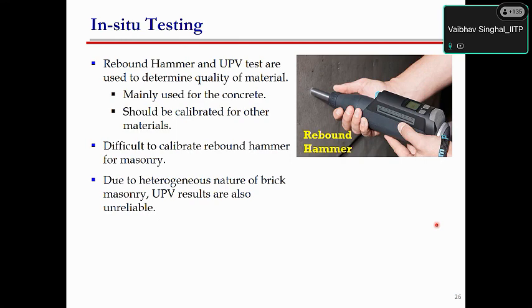You cannot use them, because the rebound hammers which are available are mostly calibrated only for concrete. So you have to either calibrate it for a particular type of brick, or you need to test a lot of bricks and then find out some kind of calibration curve, so that if the rebound values are these, this can be interpreted as this much brick strength. So a lot of data has to be collected, and the rebound hammer has to be calibrated for masonry structures. But the challenging thing is that you can only know the strength of a brick. You cannot know the strength of a masonry. For that, you also need to find out the strength of the mortar and then use some equations.